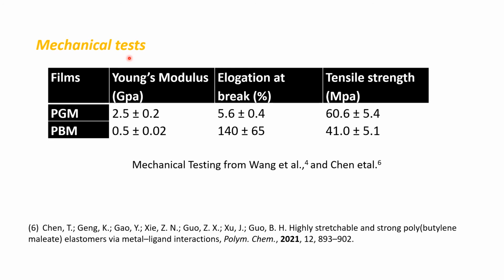So this is the mechanical properties result from PGM and PBM as comparison. It can be seen that PBM has poorer Young's modulus and tensile strength. On the other hand, it shows higher elongation at break because of its elastomer properties. The PGM polymer shows better Young's modulus and tensile strength and poorer elongation at break. The PGM prepolymer modified by 1,4-butanediol will have partially elastomer properties like PBM and will enhance the tensile strength and Young's modulus of the PBM produced.